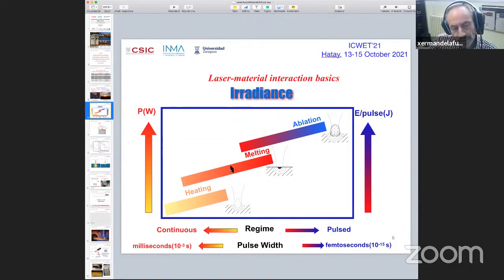As you go to the pulse regime, or you can increase the intensity of the CW radiation, you can induce melting on the surface. And if you go to very high intensity levels or short pulses, then you can generate ablation, which is removing material from the surface.